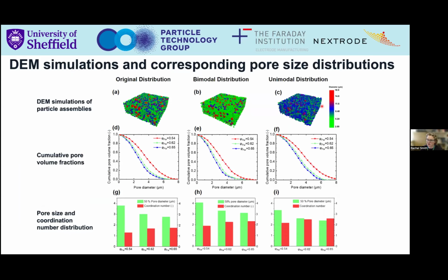So in order to do this work, we had to generate quite a lot of different structures, but we only did about 45 DEM simulations. So that's probably about 6 months of simulations, I would say. And the idea, as I said, is to effectively have a model that can predict almost any condition within the boundaries of what we have simulated, okay?